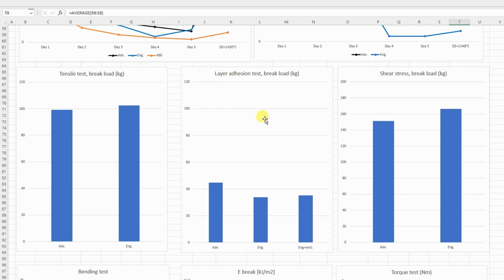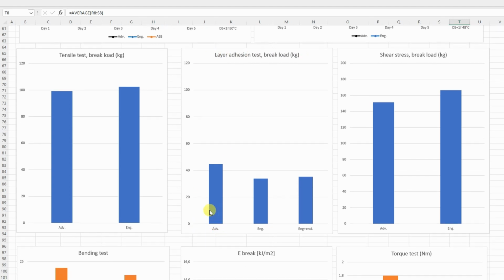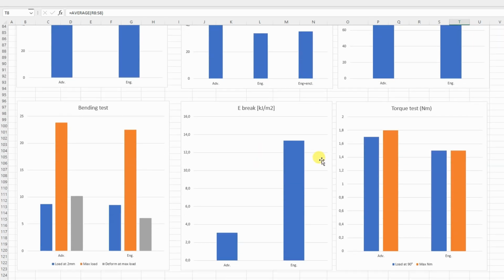Now the layer adhesion test. It's really true that the advanced PLA has very good layer adhesion. Engineering PLA, basically everything above 20 kilograms is acceptable for me, and actually we don't have too big a difference with this printing inside the enclosure. The shear stress, well, the engineering PLA was stronger a little bit, but the difference is not significant.